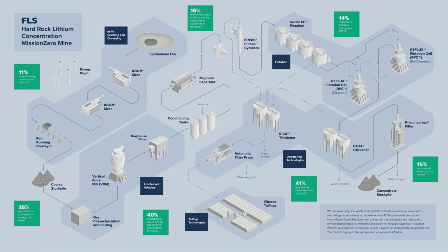So we then moved on to say, okay, we need to produce the 6% spodumene concentrate to feed this. So we developed a hard rock lithium flow sheet with stacked ABON sizers with hardened teeth, dry grinding with our vertical roller mill, that was out of the cement industry. And then we were using next step flotation, which is conventional flotation with energy efficient rotors in, and then our reflux technology for the cleaners and recleaners afterwards. Going into thickeners without drives, which are our ECATs, and then filtered tailings.